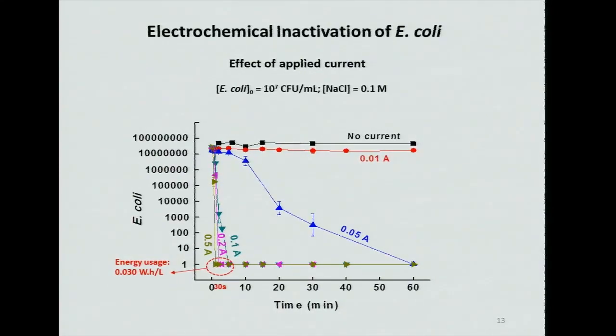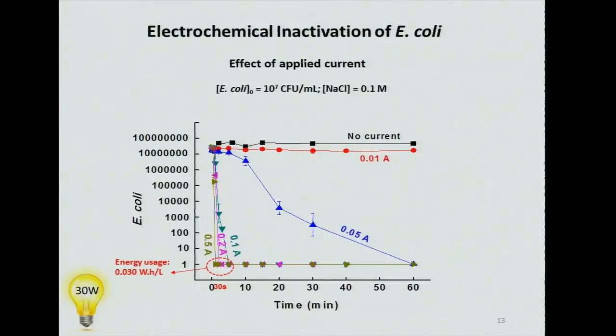And that's very fast. And the energy usage for this inactivation was about 30 milliwatt-hour per liter. How much is this energy? This is like you turn on a 30-watt lamp for 3.5 seconds, which is not that much.